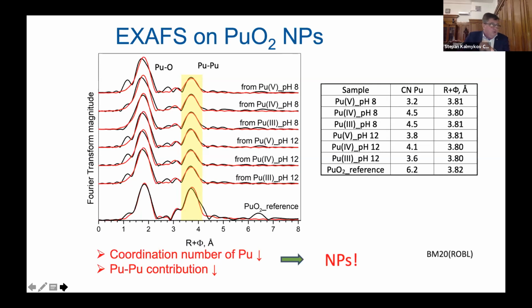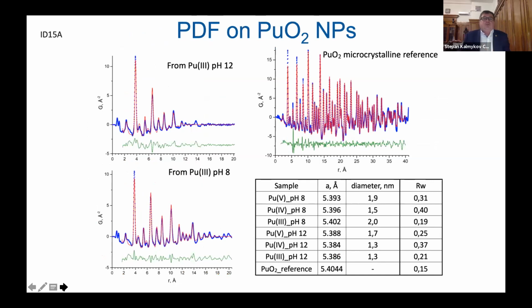plutonium O2 references. Another very powerful technique that could be used to trace the long-range order of the nanoparticles, not only to determine the particle size but also the pair distribution, is presented here. So this is a pair distribution function of these plutonium O2 nanoparticles. As you can see, again, this data supports the X-ray diffraction and TEM measurements. We really deal with very small nanoparticles with a size from 1.3 to about 2 nanometers, independent of the starting redox state of plutonium and independent of the conditions in which these nanoparticles were cooked.